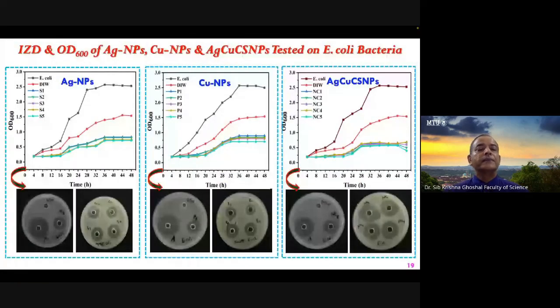We go for a further measurement called inhibition zone boundary measurement. This is a standard biomedical measurement technique, where we measure the optical density as a function of time. In the lower part, you can see on the Petri dishes, these bacterial cultures, E. coli culture, and we put samples drop-wise. We have 5 samples. For pure E. coli, we measure the optical density. For deionized water, we measure the optical density. We measure the optical density for our 5 samples that we produce at 5 different laser energies.